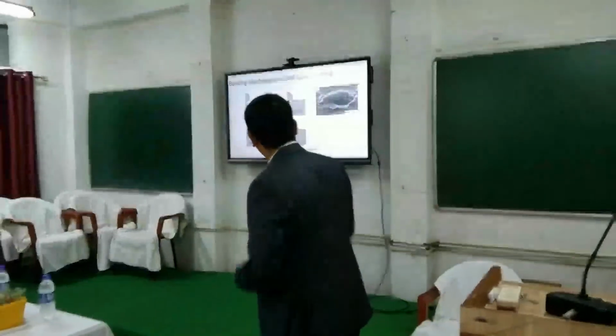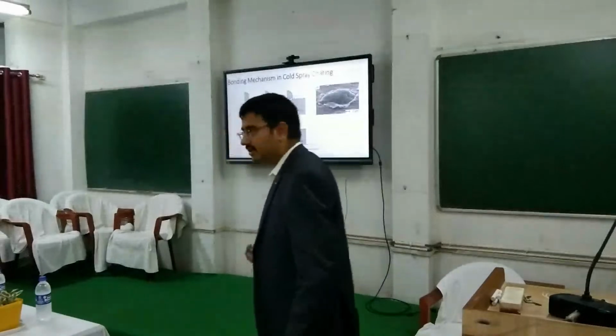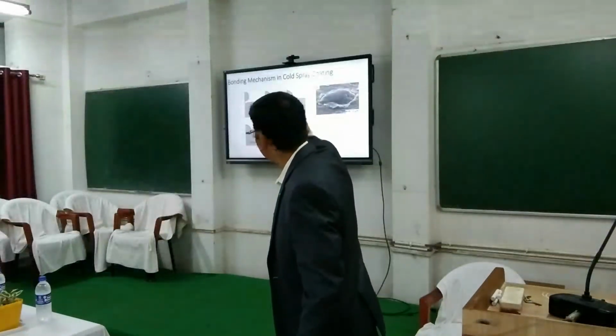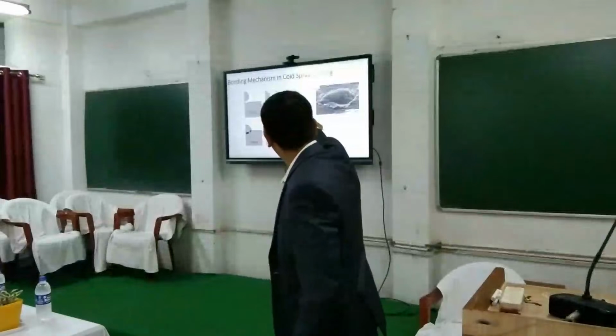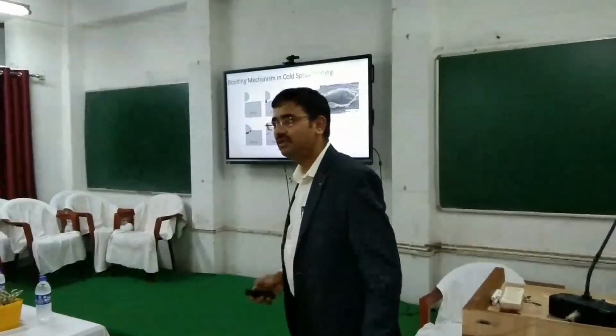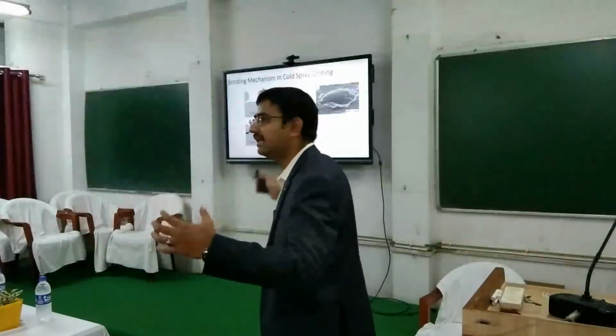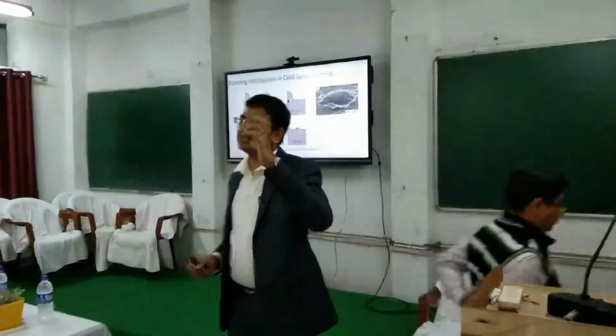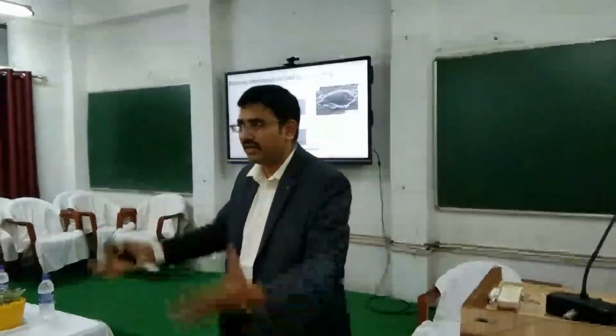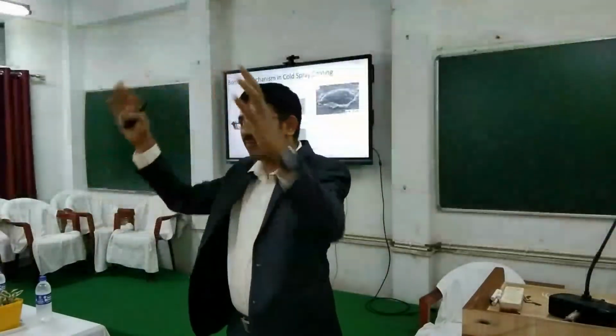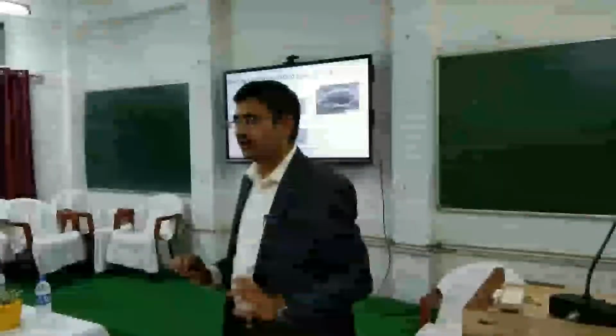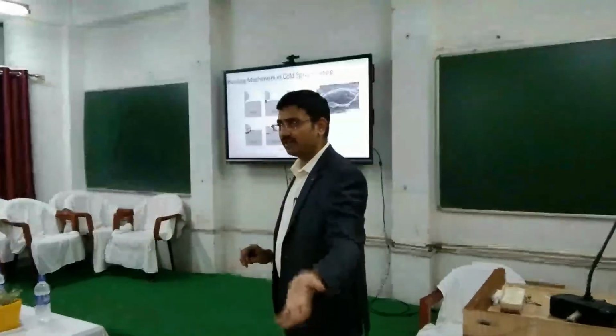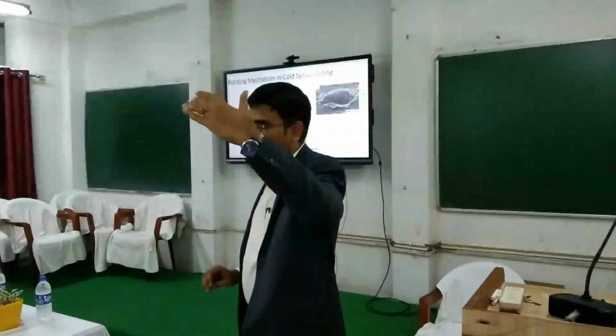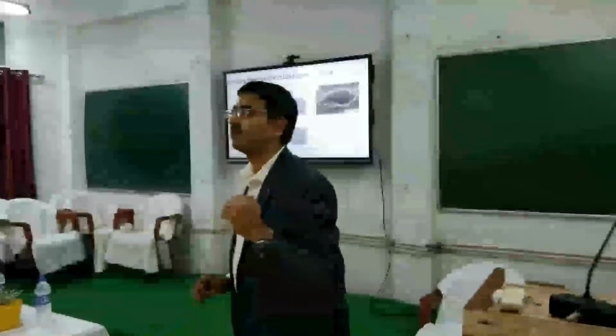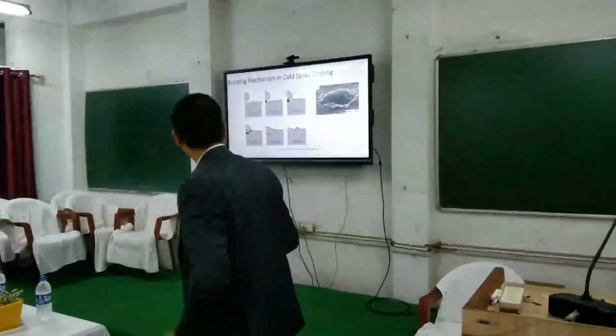So this is the bonding mechanism as I have discussed. The particle impacts, and you have the plastic deformation that occurs in a very negligible region, and that is the jetting action, and the particle actually bonds to the body. The bulk of the particle temperature is at a very low state, whereas only at the interface, due to the impact, the temperature will be high. But since there is a bulk substrate, the heat dissipation is faster, so the bulk of the material stays at very low temperature. Cold spray does not mean it is below room temperature; it is only that the temperature of the particle is much lower than its melting point. That's why they have termed it the cold spray process.